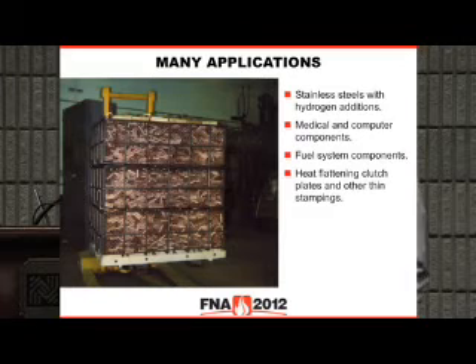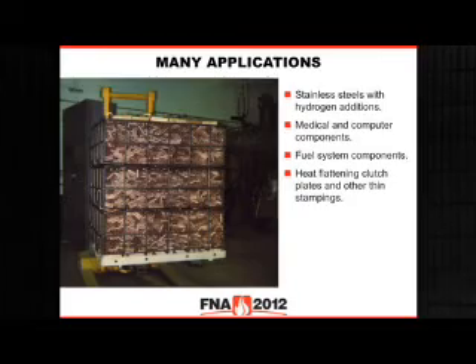We've got applications for beryllium copper. So there's people doing electrical contacts, springs and clips. It's typically done in the second process at about 600 degrees, so it's a nice application for the furnace. You can do all your alloy steels. You can do stainless steels, but we typically recommend a 4% hydrogen addition with the nitrogen. It'll keep stainless bright. You'll get some discoloration. And again, discoloration's in the eye of the beholder. One guy can look at that and say, that's the most beautiful part I've ever seen, and somebody else look at it and throw up. So we typically, when you get into the stainlesses, will recommend a 4% hydrogen addition.